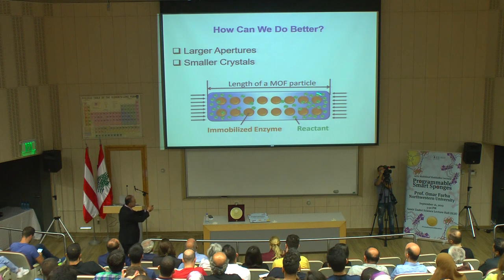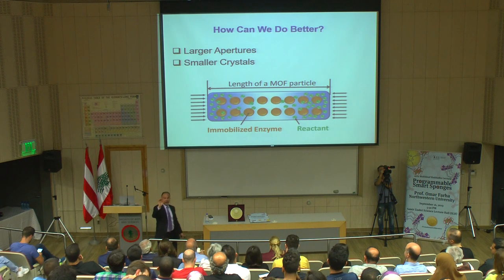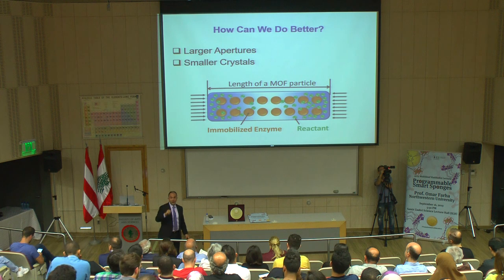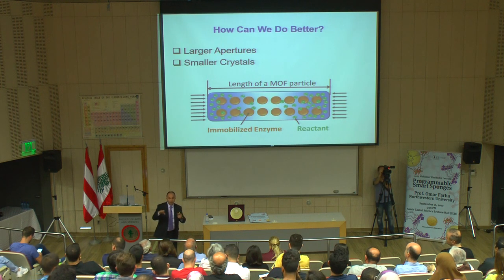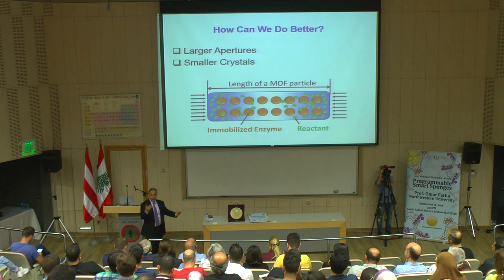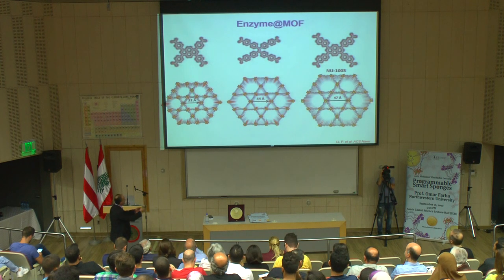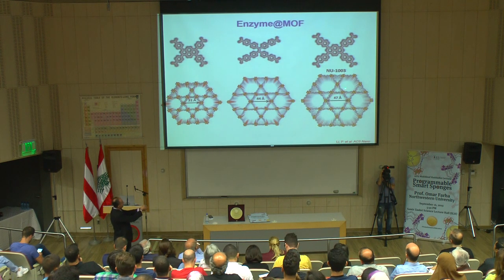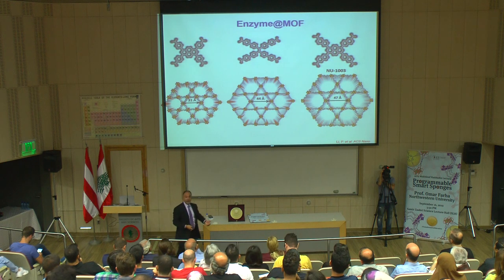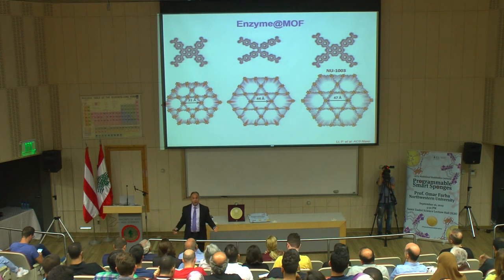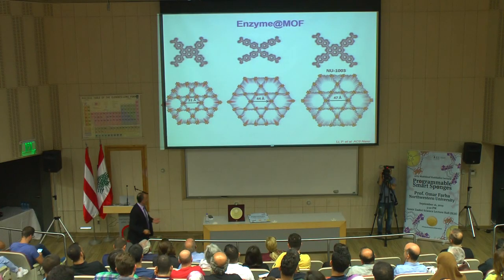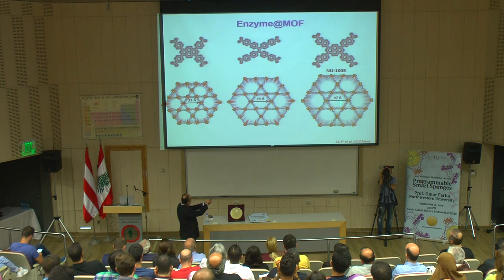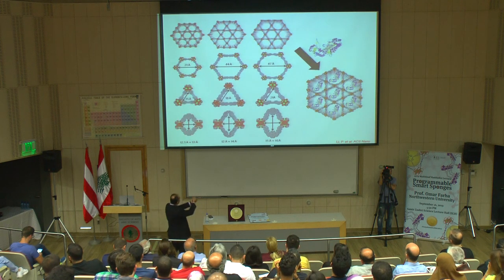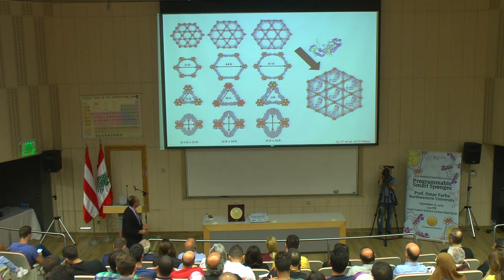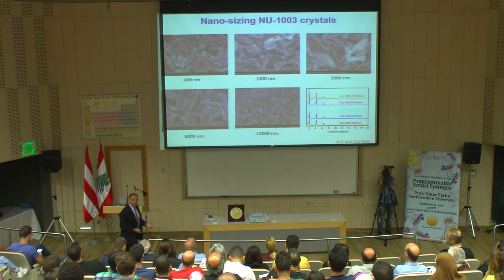It is by making the crystallite smaller, or you make the triangular channel larger for things to go in and out faster, and those windows between the channels larger for things to diffuse even faster. We made another material called NU-1003. So you could see we make a lot of organic linkers. We collaborate with Sir Fraser to make some of those linkers, and others we make ourselves if needed. We made NU-1003 with larger channels. We put the enzyme in the same way, so I'm not going to go through that. But we need to characterize that.